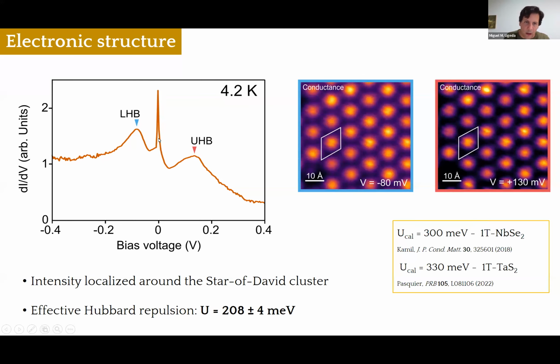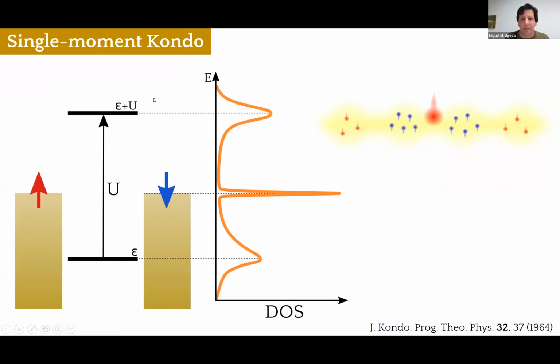In particular, because we also see a sharp resonance at the Fermi level, which basically coincides with the fingerprint of a single moment Kondo. Basically, we have 2 states. This is one impurity state. This is the impurity state plus the Coulomb repulsion, and a sharp resonance, which is the fingerprint of a single ion Kondo due to virtual transitions undergone in order to screen this isolated magnetic moment.